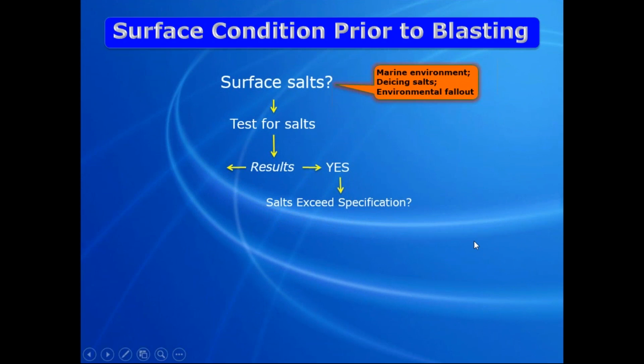And for using our products, you think about the marine environment, de-icing salts that we had talked about before. And if you do find excessive salts, there's nothing in writing yet by NACE and SSPC and ISO, but they're all working on it now to come up with a standard. And as we speak, the standards are generally made by the owner of the equipment. But mostly what we're seeing in the industry is that anything for immersion, submersion, buried pipeline, tank bottoms, things of that nature, the industry is requiring about 3 micrograms per centimeter square or less for those types of conditions.